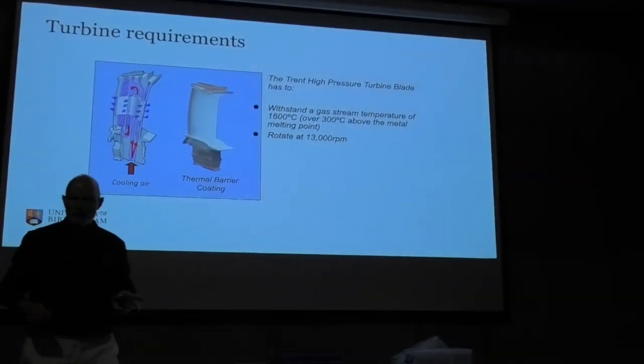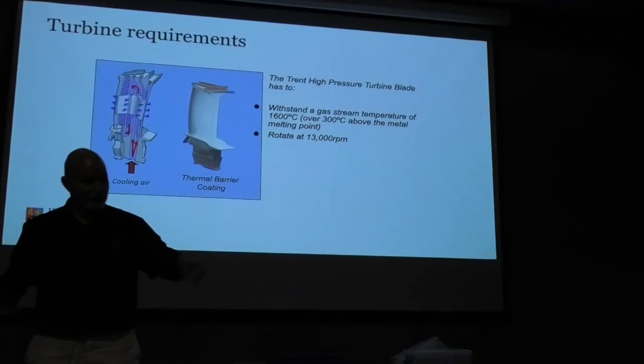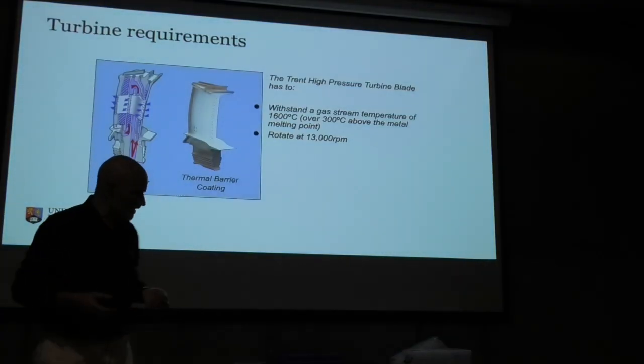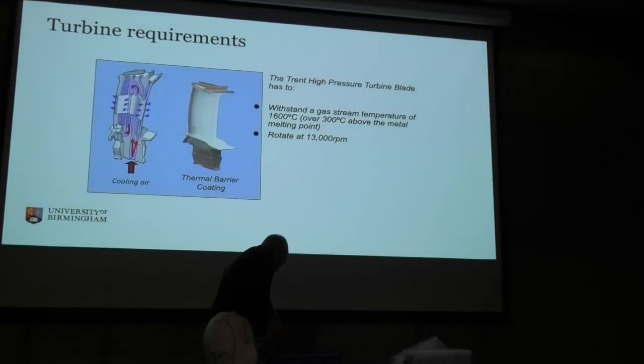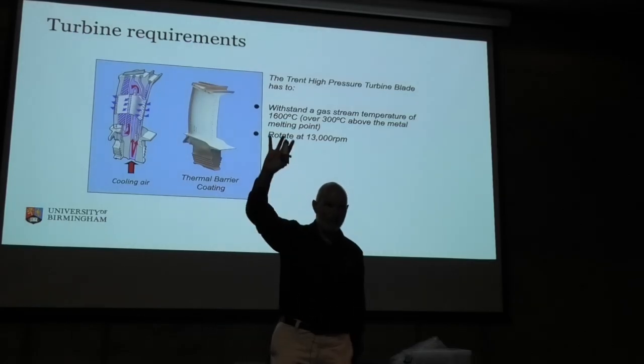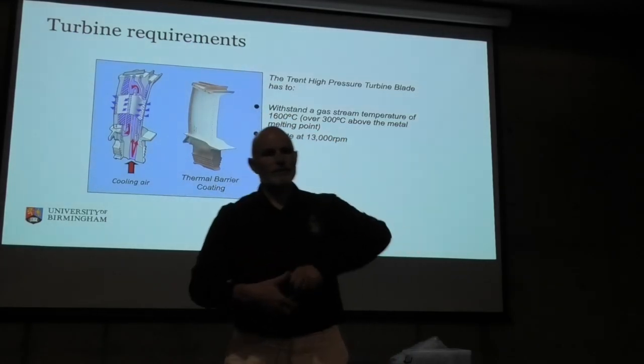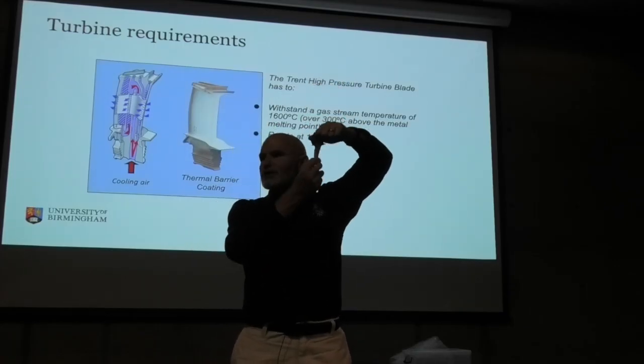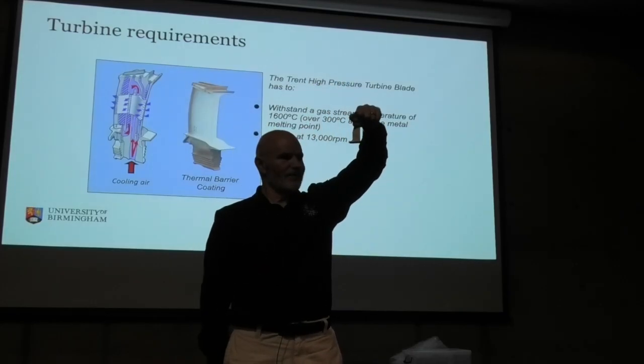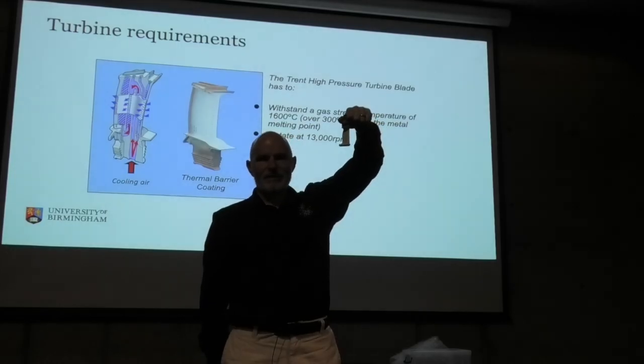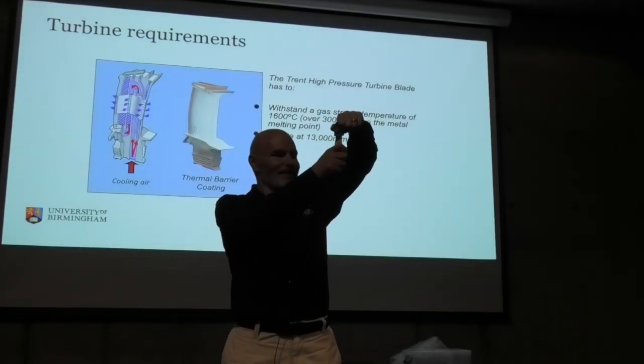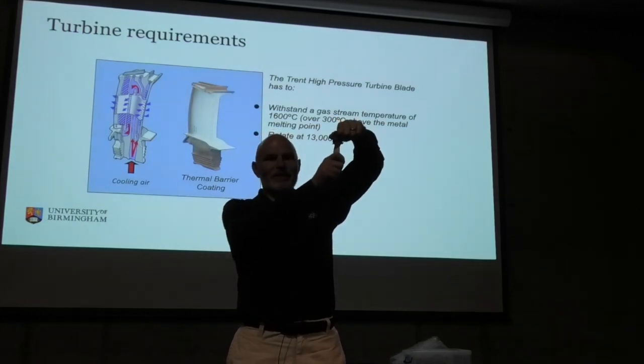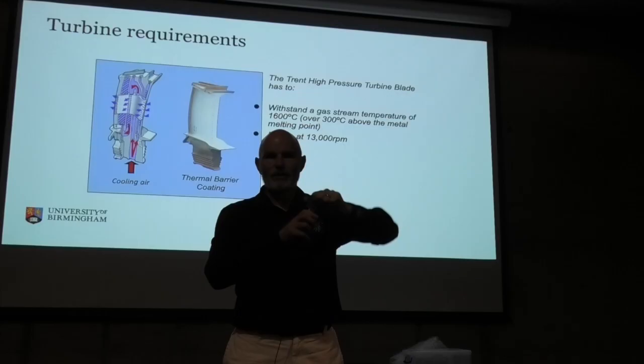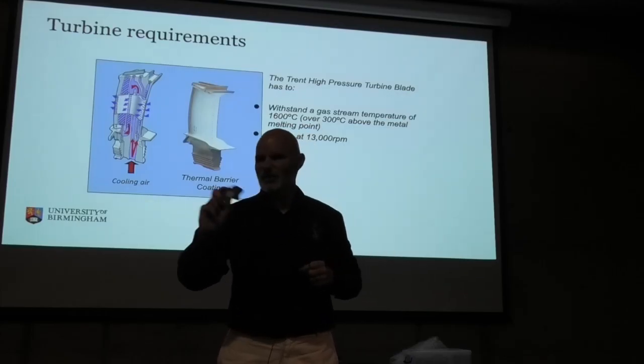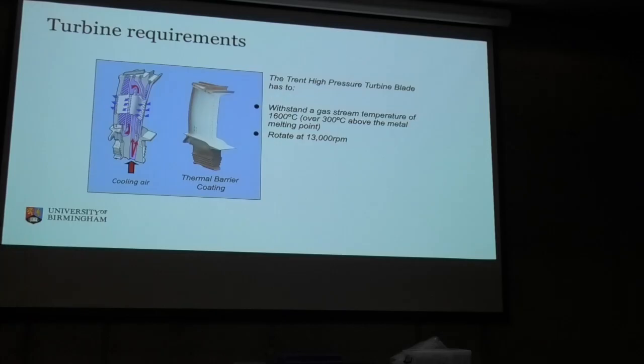We're going to rotate these blades at 13,000 RPM because we need to spin them in the gas stream. That's the equivalent of taking one of these blades. There you go, one of these blades. And if we grabbed it by the root and hung a lorry or a bus off it, it would be about the same weight. Now there's 60 odd of these in a set. And what we're going to say is we're going to hang it by that. And every blade has got a bus hanging off it statically. We're going to spin it that fast that this root block has got to take those kind of loads. It's about 18 to 20 tonnes. It'll keep us quiet for a bit.